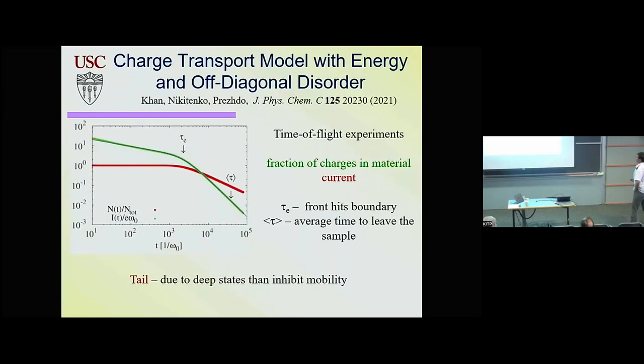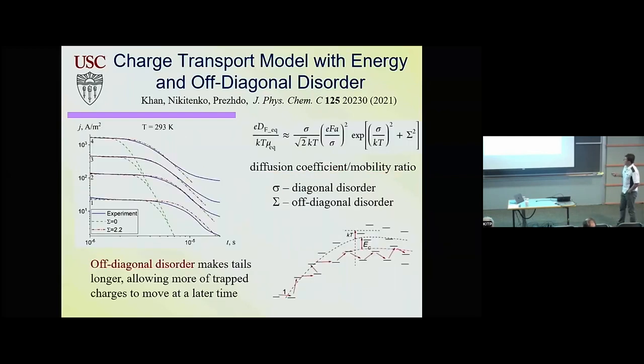And then the other one is the same kind of model. Now I'm talking about so-called time of flight experiments, where you have a material, you create charges, and charges move, and you collect them at an interface. What's plotted here is the fraction of charges that remain inside the material, and this is current. First you have a big wavefront that hits, and then current is continuous, and then eventually when the biggest number of charges escape, you still have current remaining, you have a tail, but it's decaying because the mobile charges escaped, and you have charges that are left in the trapped state. And again, you have this very weak tail that lasts for a long time.